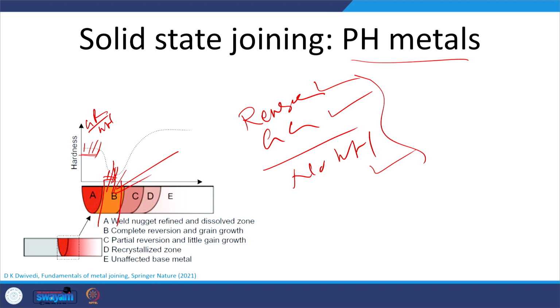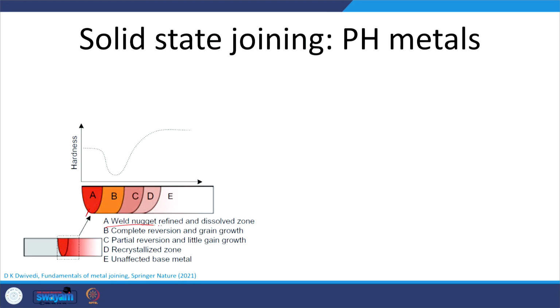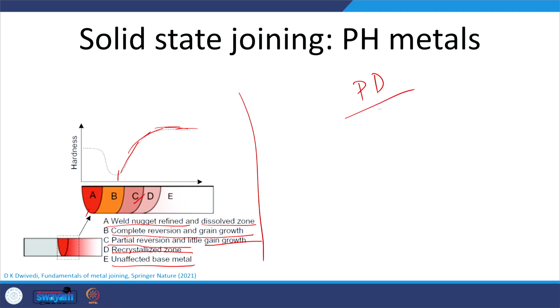like friction stir welding. And that is what we see here: in the nugget zone A, the weld nugget is refined due to dynamic recrystallization, but it is completely free from any kind of precipitate, so the all-dissolved zone is formed. Complete reversion and grain growth take place in zone B, reversion is partial with little grain growth in zone C, and there is recrystallized grain in D and then the unaffected base metal. So, after the B zone we have increasing hardness and strength. Okay. So, this is about the precipitation hardening metals,